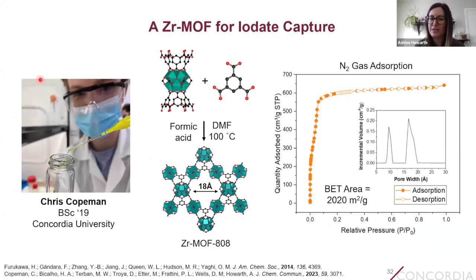And so the MOF that we wanted to study for this application, the removal of iodate from water, is zirconium MOF-808. This was a MOF that was first reported by Omar Yaghi's group in 2014, and we thought it should be perfect for this application because it has these quite large 18 angstrom pores, which can accommodate iodate oxyanions. It's made of these 6-connected hexanuclear cluster nodes. So because they are 6-connected, meaning they have 6 connections to make the framework, they also have 6 empty connections or open metal sites that are potential spots that the oxyanions can interact with.